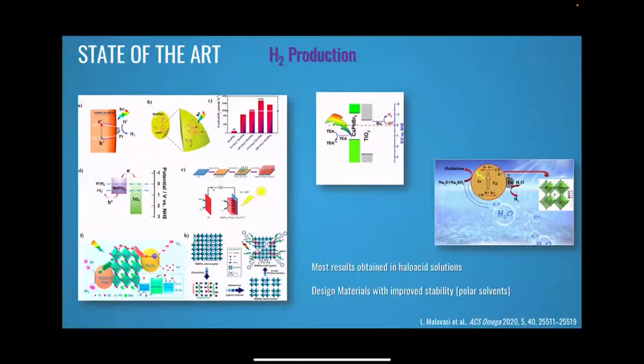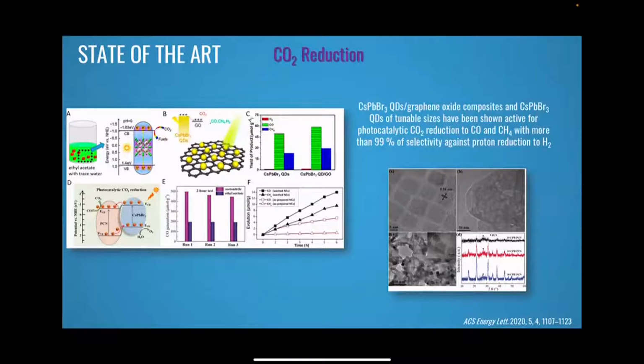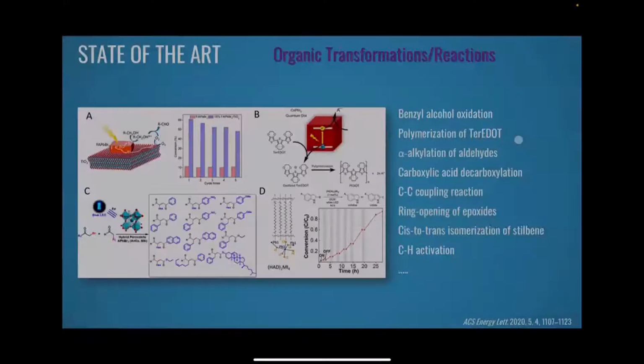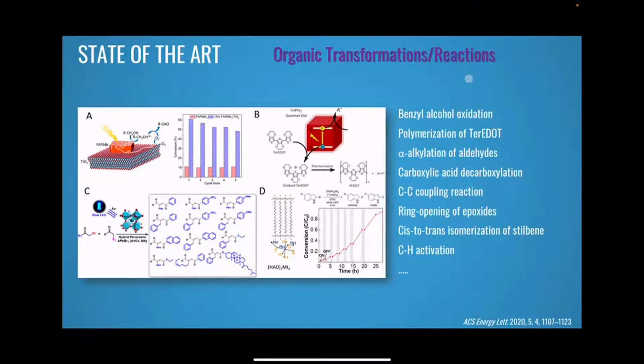The state of the art is that they have already been extensively investigated, for example, for hydrogen photoproduction. Here you see, for example, one of our recent reviews on the use of metal halide perovskites for hydrogen photogeneration. I will not go into details, but many different phases have been used. They have been applied also for CO2 photoreduction. Okay, so for example, in this case, quantum dots of this size, more or less 10 nanometers or even less, have been used in composites with graphene oxide to reduce CO2 to carbon monoxide and methane with, you see, a very impressive selectivity against the proton reduction. They have also been applied for photo-organic transformation reactions.